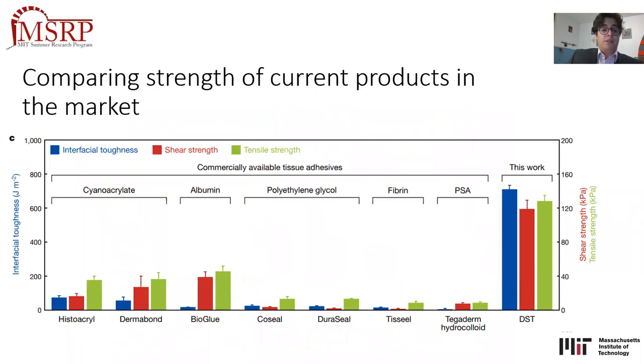DST demonstrated that it had superior adhesion performance compared to other tissue adhesives, as well as better timing for adhesion, between 5 seconds and 30 seconds. Shear strength, interfacial toughness, and tensile strength were compared amongst the products, and DST showed remarkable results.